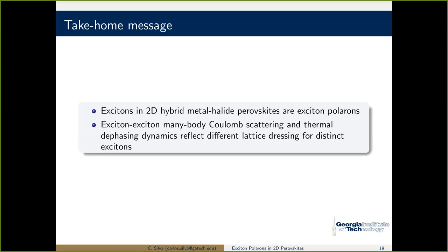That's right. So we don't have at the moment a very good resonance Raman spectrum that covers a range where these modes would be important, but we do have non-resonance Raman spectra from Vlad's master thesis. The way we did the impulsive vibrational experiments was with pretty long pulses, because they optimized the region of the vibrational spectrum for these in-plane phonons. We haven't done this with much shorter pulses, which is what it would take to access the spectral region where the higher energy vibrations would also couple. So that is something that has yet to be done.